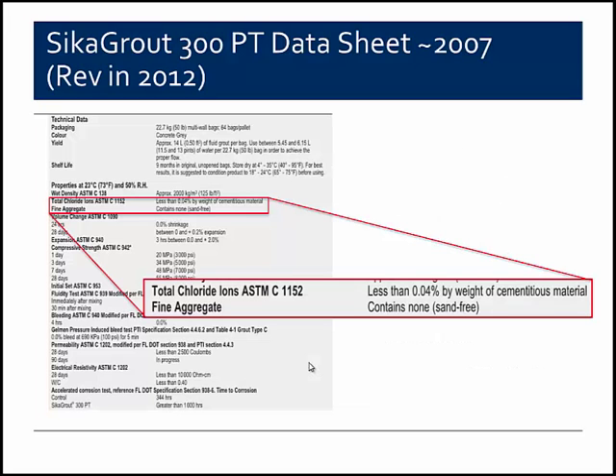And this is the second page from that same data sheet. Here Sika is actually saying that during their trial batch evaluations of their grout, they were at half the rate of the total chlorides allowed by PTI. And then once again, they say that there are no fine aggregates in the mix. Now, the reality is, though, there are still some inert fillers in this product, and it was a calcium carbonate inert filler, which was not actually called or characterized as an aggregate. It's more correctly characterized as a filler, but it was not reported on this data sheet.